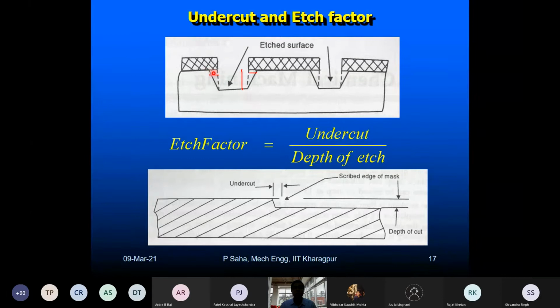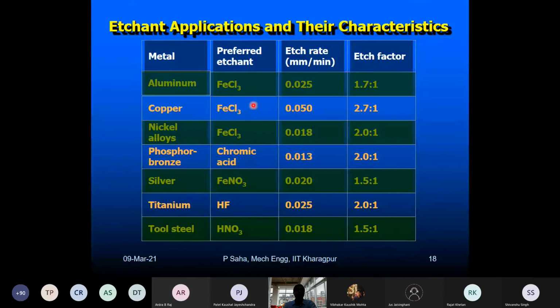This is known as undercut, these portions. So the mask is up to this, but the actual side machining on the top is up to this. Okay, so this is what is called undercut. Okay, and the etch factor is the ratio of the undercut divided by the depth of cut. Okay. So for different etchants, their characteristics are different. Like we can have a whole lot of etchants starting from ferric chloride, chromic acid, ferric nitrate, hydrofluoric acid, nitric acid, and so on. Sometimes we also use mixed acids, HCl and HNO3 together. Okay, it all depends on your application, which metal you are machining.